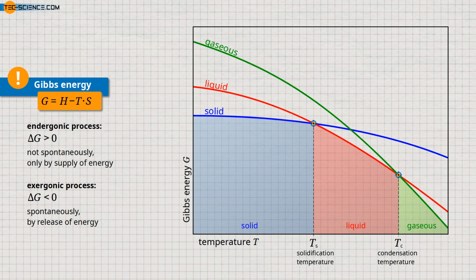If the temperature falls below the solidification point, the liquid state is no longer stable due to the higher Gibbs energy. Rather, a decrease in Gibbs energy occurs during the transition from the liquid to the solid state. Therefore, below the solidification point, the Gibbs energy decreases as the state of the substance changes from liquid to solid. This phase transition thus strives to take place spontaneously, and the substance will change to the solid state with the lower Gibbs energy, releasing energy in the process. The difference between the Gibbs energies of two states thus represents the drive for substances to change their state of matter when falling below or exceeding a certain temperature, thereby assuming the state with the lowest possible Gibbs energy.